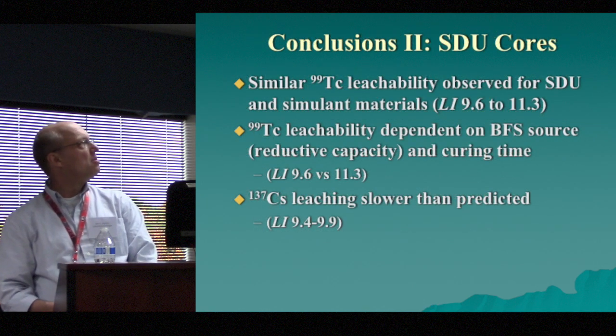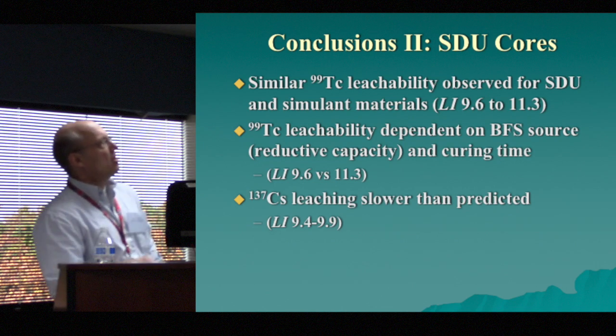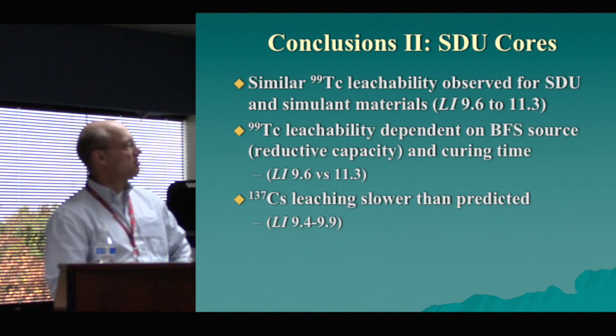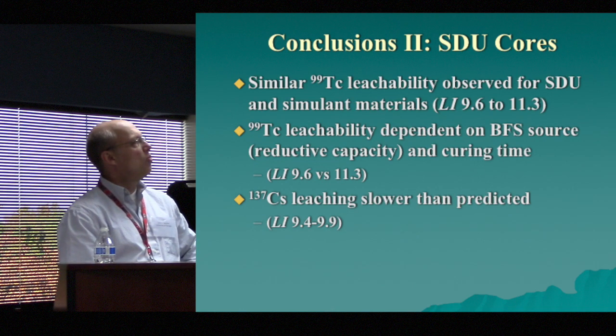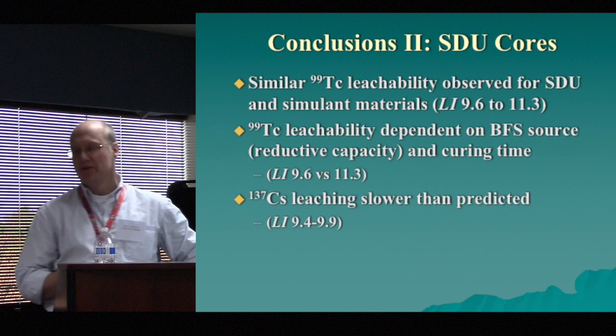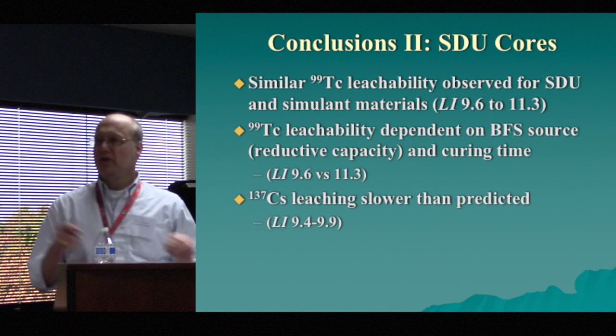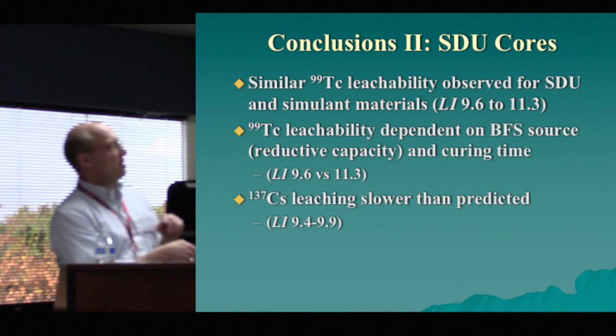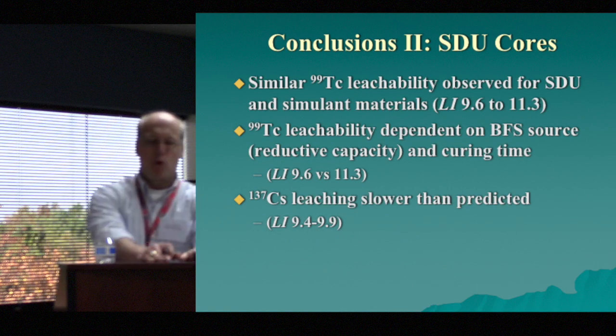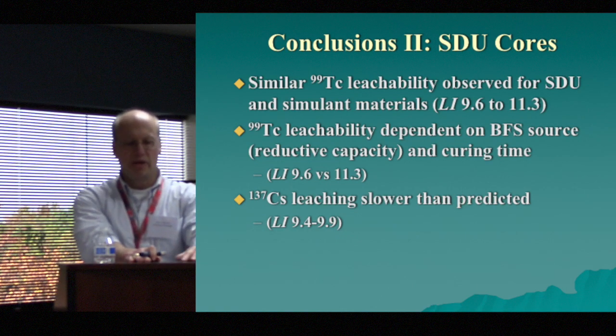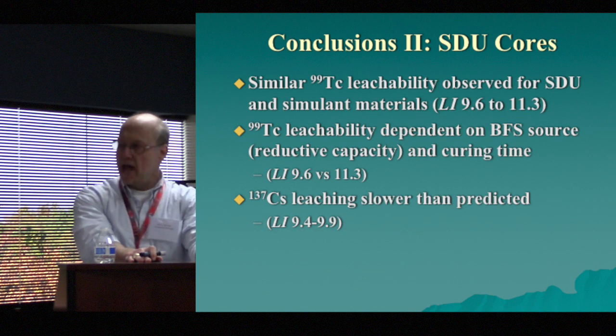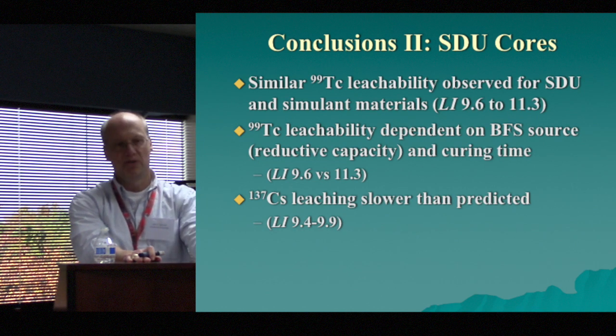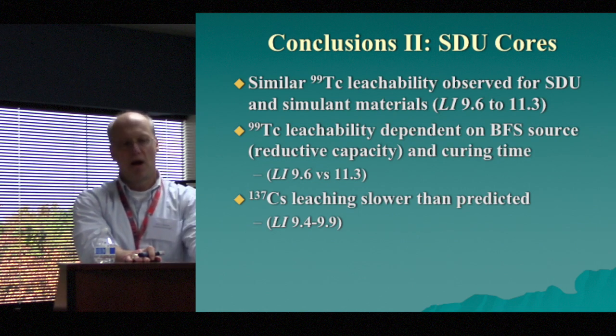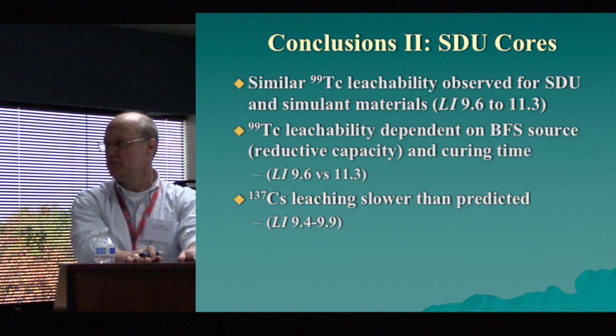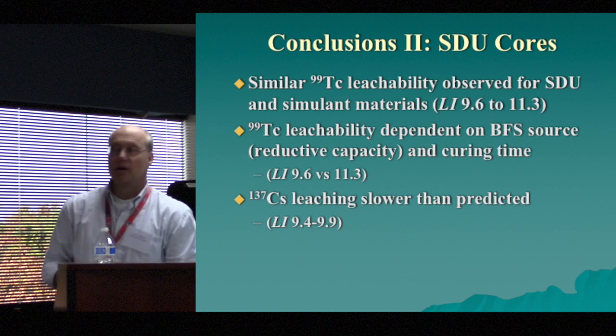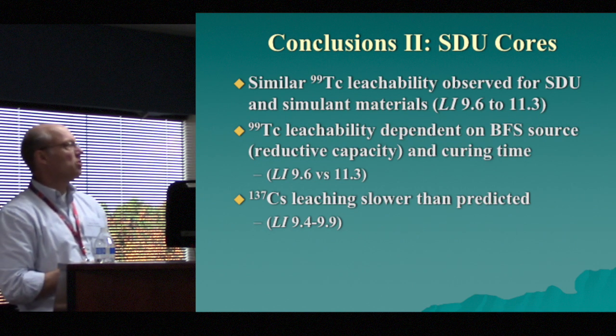Next slide, please. For the SDU cores, we got similar Tc leachability observed for the SDU cores and the simulant materials. We did seem to have some kind of indication that the blast furnace slag source and curing time were important. One of the things that's interesting to note is that before this, if you look at a lot of the literature and a lot of the different tests, it didn't really seem to matter. Every lab and every experiment that tried to measure the reductive capacity of these different blast furnace slags almost always presented a number that was very similar. It didn't seem to vary that much between different materials. But that was very different from our newer source.